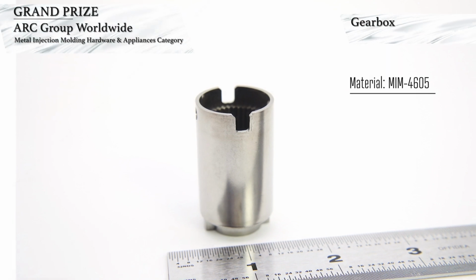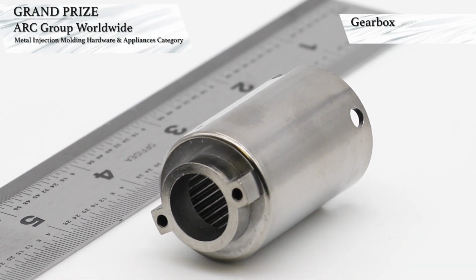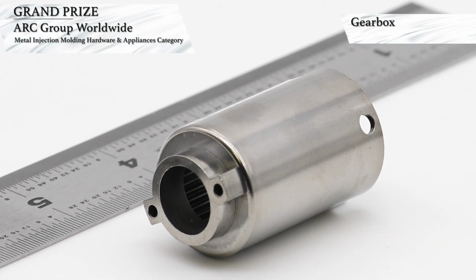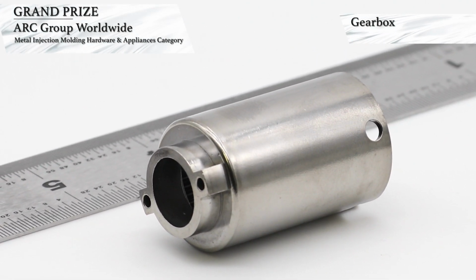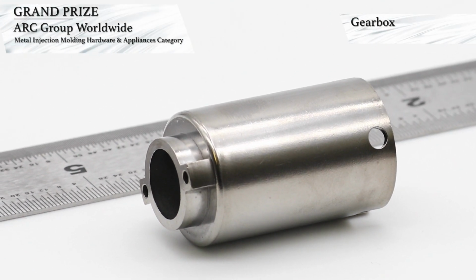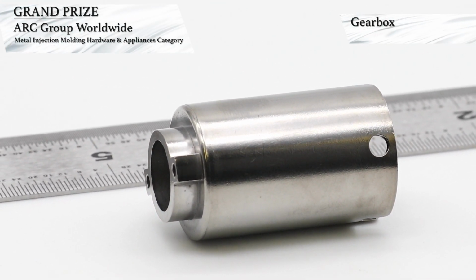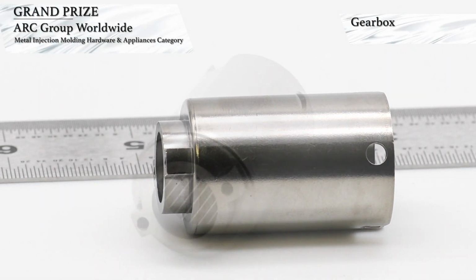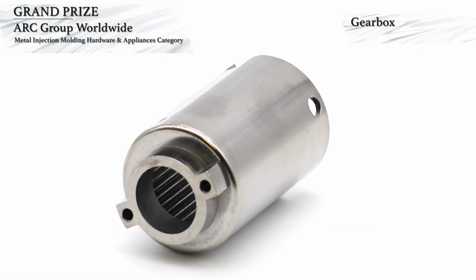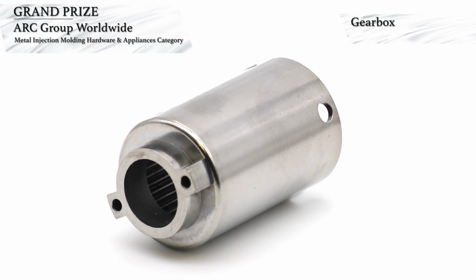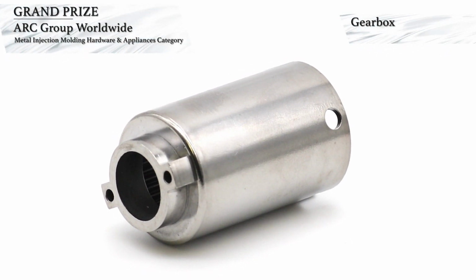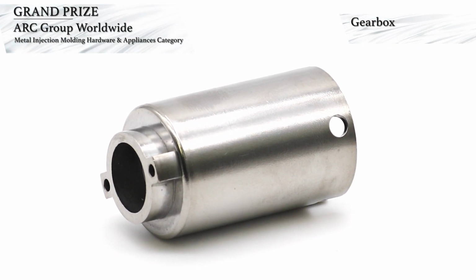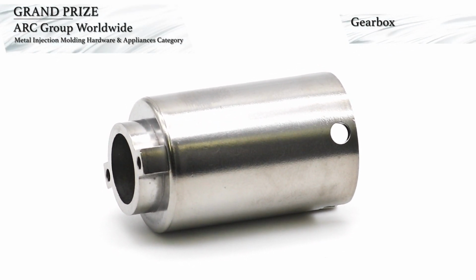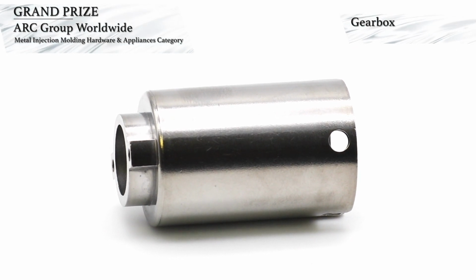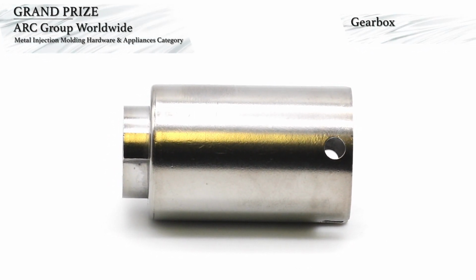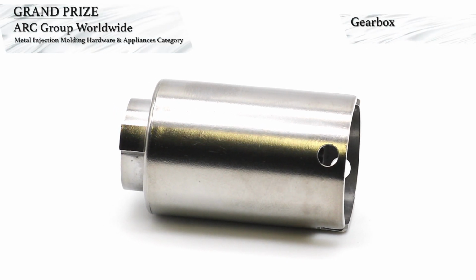Strategic tool design was implemented to allow the 25mm diameter by 63.5mm long core to actuate without causing unintentional damage to the part. Careful timing of slides was required, along with precise draft angles to permit acceptable part removal from the tool. The greatest challenge is the 41 gear-teethed splines on the entire inside diameter of the part. Each part is carefully inspected for debris or damage to the gear teeth. Parts require gentle handling in the green state, and the tools need frequent cleaning. Sizing is necessary due to distortion during sintering.